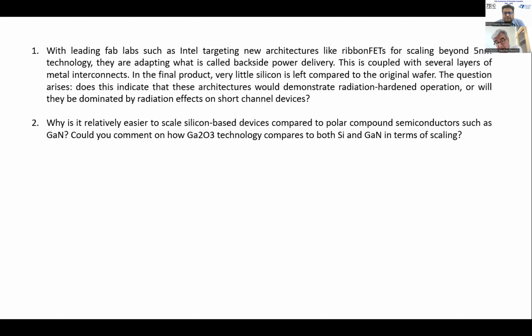The compound semiconductors usually don't have as high a thermal conductivity, so they're harder to grow. They have two sublattices, right? So you got gallium and arsenic, even for gallium arsenide. So you get anti-site defects, more native defects. So compared to silicon, they have more defects. They're more expensive to grow.